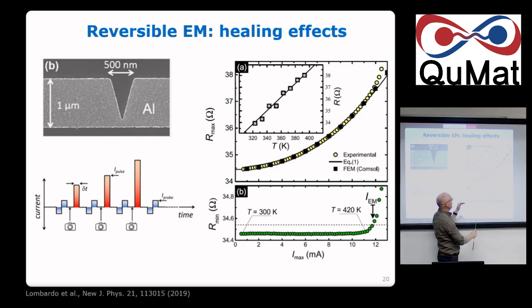This is basically this curve, and this is the small resistance you get out of this measurement. So it's when the system is cold and stable, and after applying a big current you see nothing changed, and then you reach the electromigration current, and you see the system start to be modified, moving atoms. So we can look at this one.